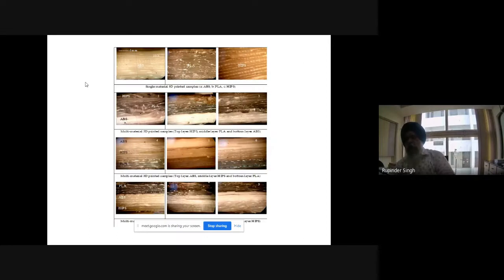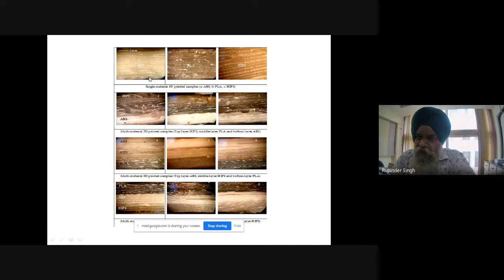Now this is really important for the antenna engineer. I am interested in their photomicrographs. Here you see a photomicrograph of ABS taken at a magnification of 30x. You can see there are some patches. These patches show that the material has been deposited layer by layer: one layer over another, then another, then another. The similar thing you can see in PLA. There are some patches; this is basically a staircase effect. Similarly, in HIPS you can see there is a staircase effect.